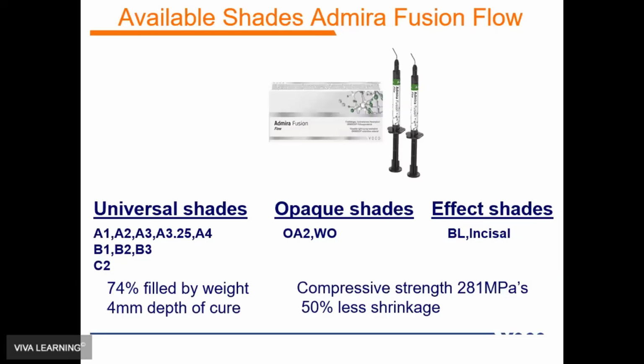This is a new proprietary product called Admira Fusion Flow. This has the same Ormocer technology and chemistry that is a complement to the products itself. They have universal shades. They're 74% filled by weight. And if you look at the compressive strength at 281 megapascals, now you're getting up there. And with the Ormocer technology, there's 50% less shrinkage. As you know, with flowables, that is one of the drawbacks. With the less filled, you can get shrinkage of 5%, 7% sometimes. With this new Ormocer technology of Admira Fusion Flow, these are certainly wonderful products that are safe and healthy as well.